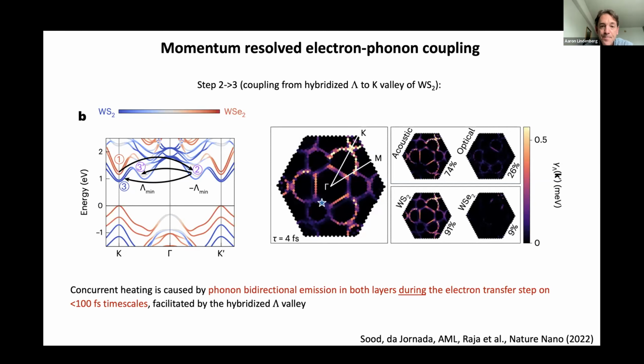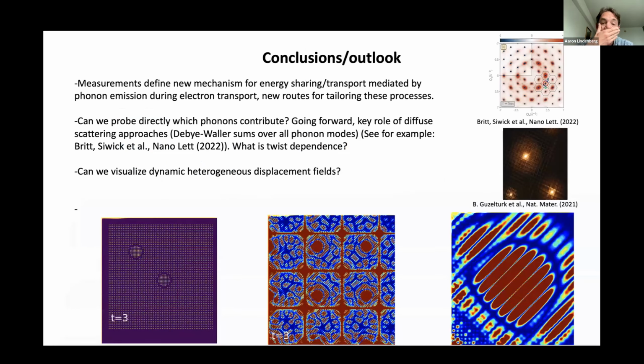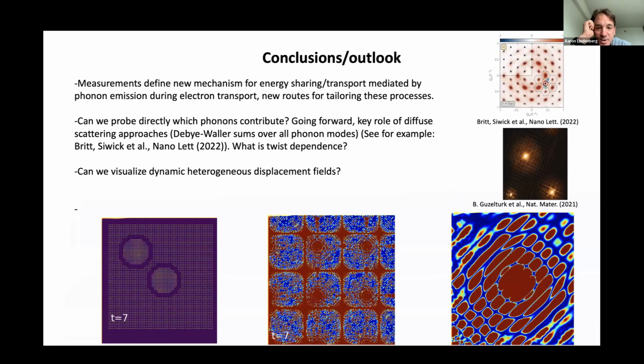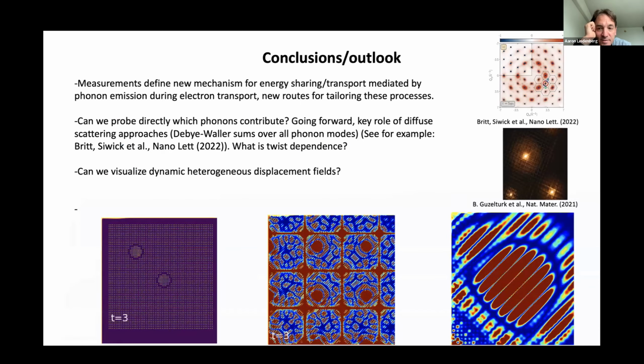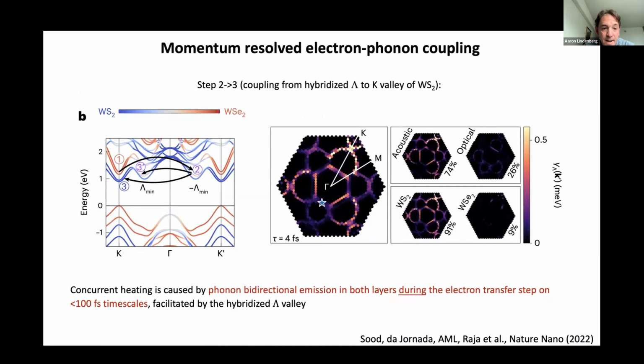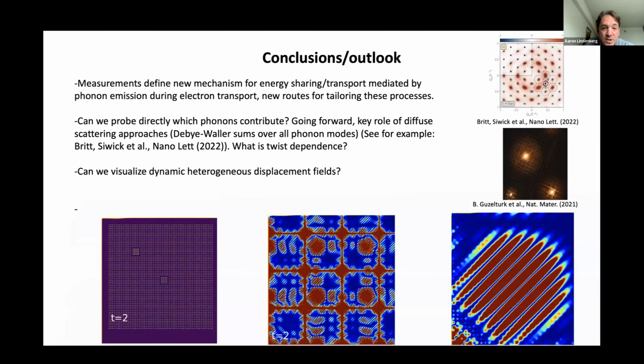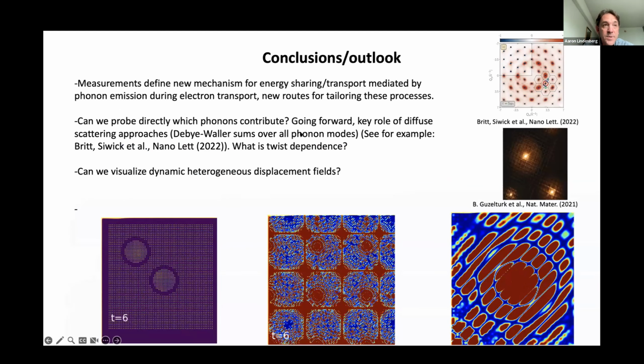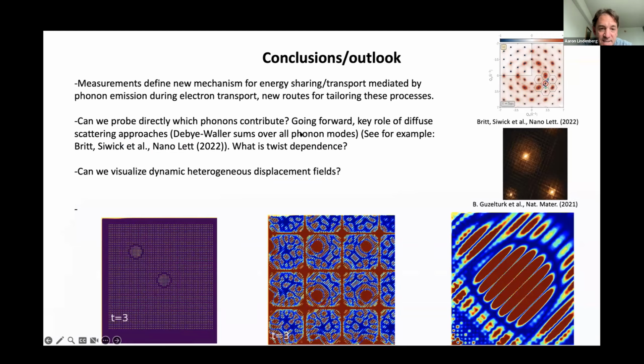Okay, so let me say a couple of comments about all of this and also some ideas and thoughts on the future. The first thing I should say is that, as you may have noticed, in our experiments all I showed were measurements of the overall temperature of the structure, right? And so we did not have direct momentum resolved measurements of which phonons were playing a role. We were measuring a Debye-Waller factor, which sums over all phonon modes in the system.